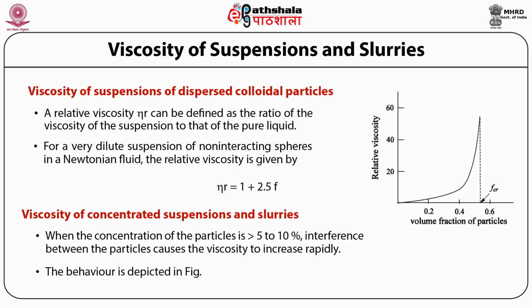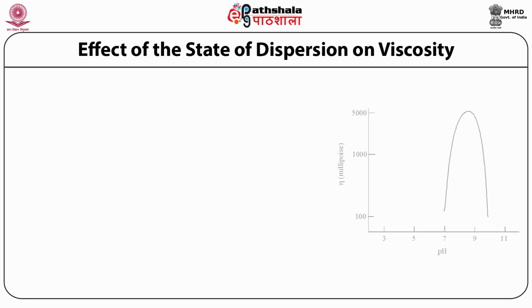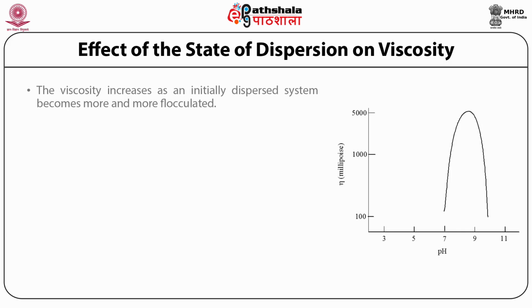A dilatant behavior can also be observed in concentrated slurries due to mutual particle interference, especially in the case where a high repulsive interaction is present. A dilatant behavior makes the pumping and handling of the slurries difficult. Now we will discuss the effect of the state of dispersion on viscosity. The viscosity increases as an initially dispersed system becomes more and more flocculated. An example is shown in this figure where the viscosity is plotted as a function of pH. Near the isoelectric point, the aggregation of the particles occurs.